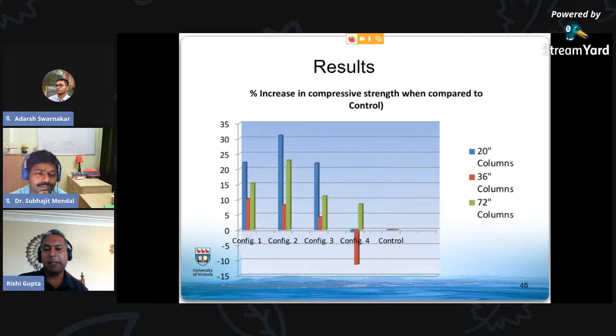the idea that a very low modulus PVC. So PVC has an elastic modulus of, let's say, 5 GPa or less. Your concrete has an elastic modulus of 30 GPa. And the idea that something which is so low modulus can actually give you confinement and an increase in your strength was truly astonishing. So we don't have much time, but there were other reasons that we believe attributed to